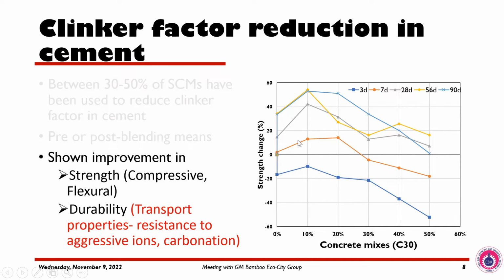And then what I did was to look at the 28-day strength. At 28 days, even at 50%, you see that we're above the C30 concrete grade. At 30%, at 28 days, we're higher than the C30 concrete grade. And then even at 90 days of curing, you see that, yes, we were still above the C30 grade of concrete. So it means that we can use these materials to decrease clinker factor and still achieve our desired strength if we limit ourselves to what is happening in Ghana and most sub-Saharan African countries.